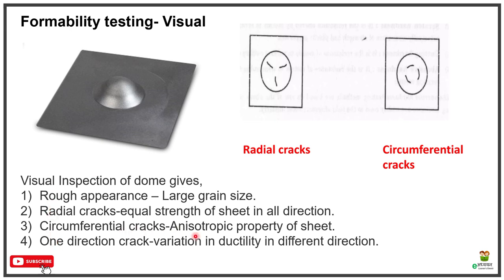Radial cracks mean the sheet has equal strength in all directions. Then the third one is circumferential cracks, which indicate the anisotropic property of the sheet. If we have a crack in one direction, then it has very good ductile property only in that particular direction, and in the other direction it does not have equal ductile property. Due to the different ductility in different directions, we cannot use this sheet in all directions for the forming process. We need to know the proper direction in which we can use it. If we use that sheet in another direction, it will fail to form the shape and generate a crack. That is not good for the forming process, and we cannot use that material.